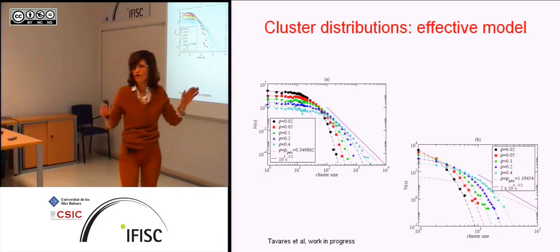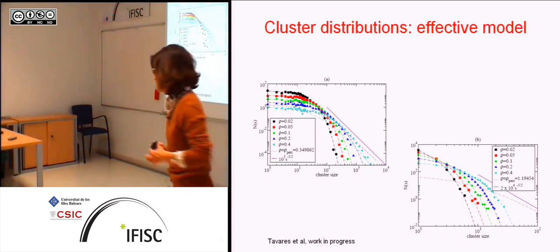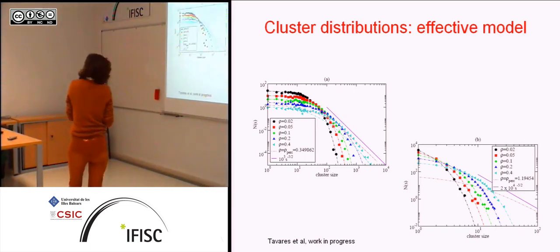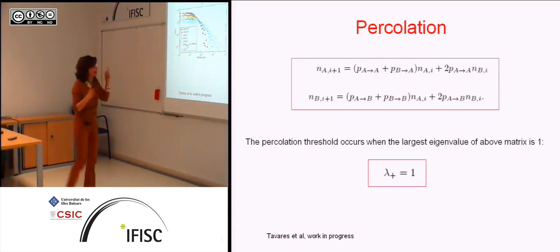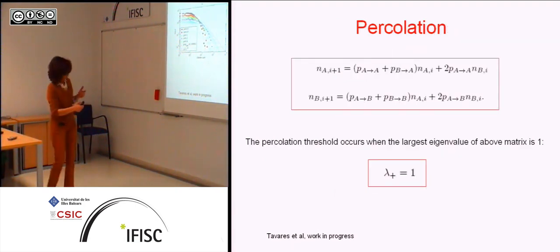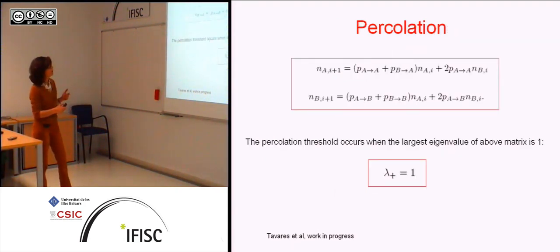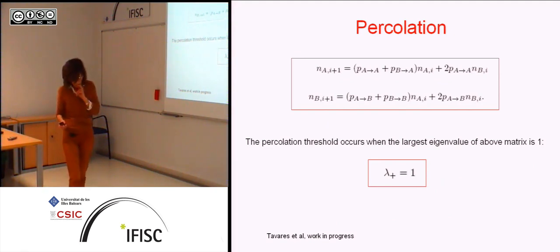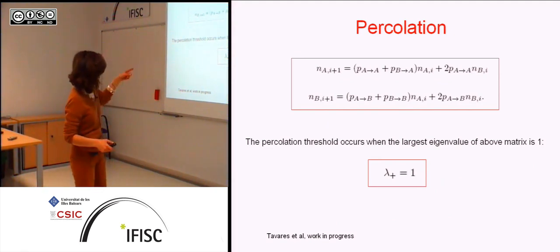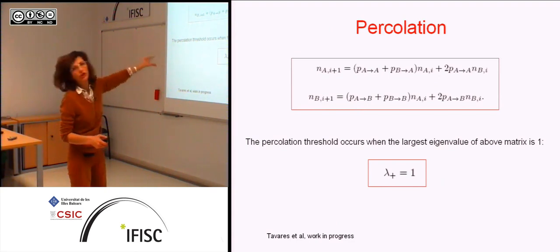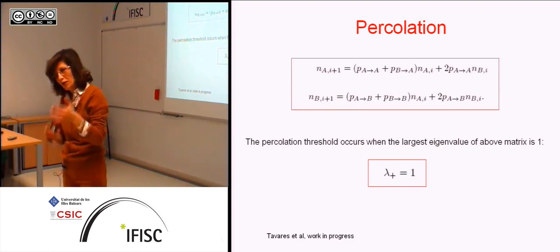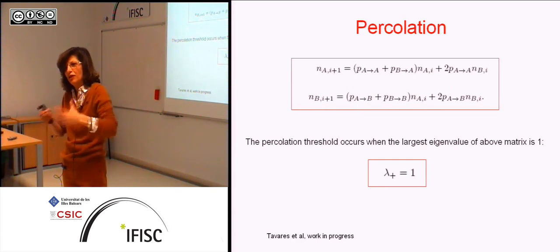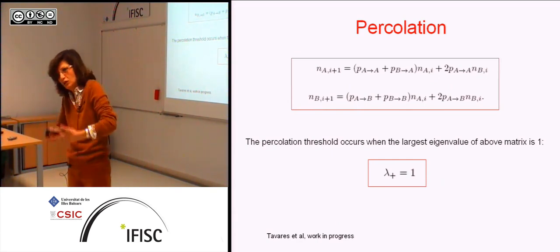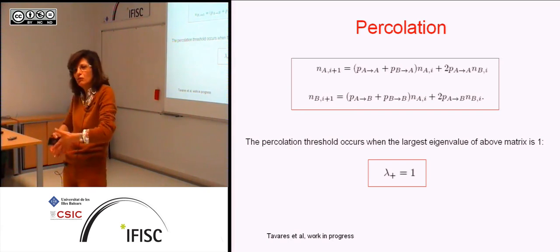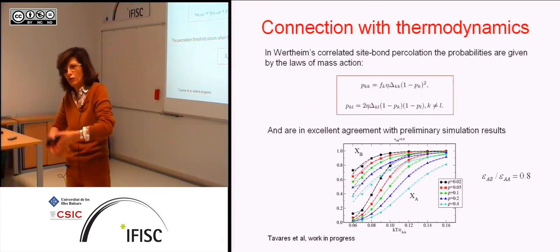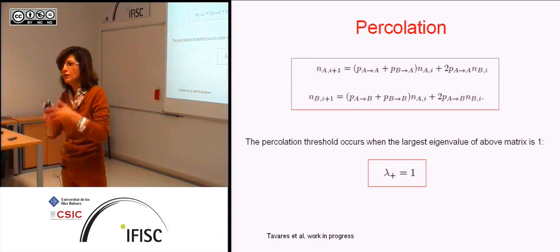Then I spent 4 or 5 months doing that. And so I came up with the idea, which he didn't believe, but now he has refined it. It's one thing we can do. We cannot calculate the distribution function, but we can calculate from this kind of structure, and also from random networks or colored random, the moments of the distribution. So we don't know the distribution, but we can know the first order moment, the second order moment, the third order moment. And now we use the following trick.